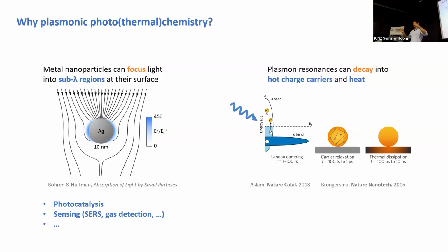Now, how do they thermalize? By scattering off each other: electrons with electrons, electrons with photons, electrons with defects, electrons with surfaces. And this kind of relaxation happens on the order of picoseconds. And eventually, it will lead to electron-phonon coupling. So the lattice of the nanoparticle will start to heat up. And then eventually, the nanoparticle that is hot will start to heat up the environment around it on the order of hundreds of picoseconds up to tens of nanoseconds. And so now we have taken the energy of a photon and we are creating heat locally.